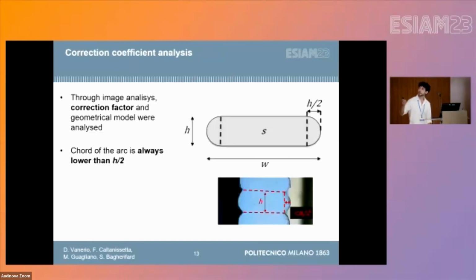After this, we considered the geometry itself, and we checked if the correction factor was actually correct also in our cases. We should have h divided by 2 as the length of this circular part, but we noticed that in our case the arc is never a semicircle, it is always smaller. So we always have a value of this length which is below h divided by 2.